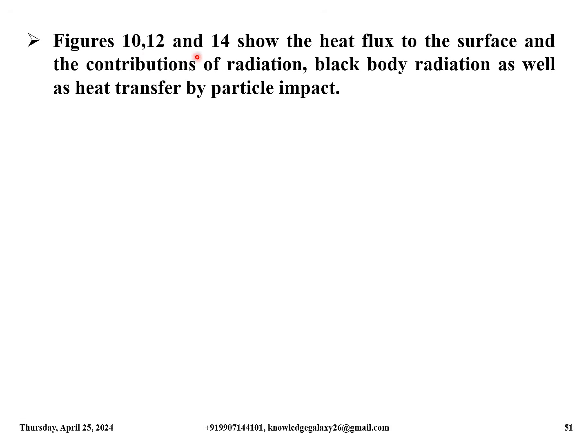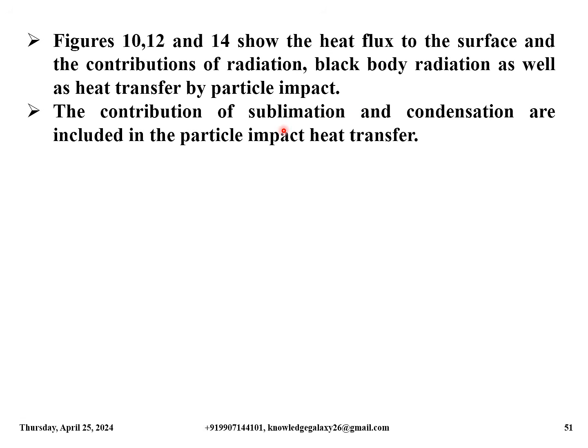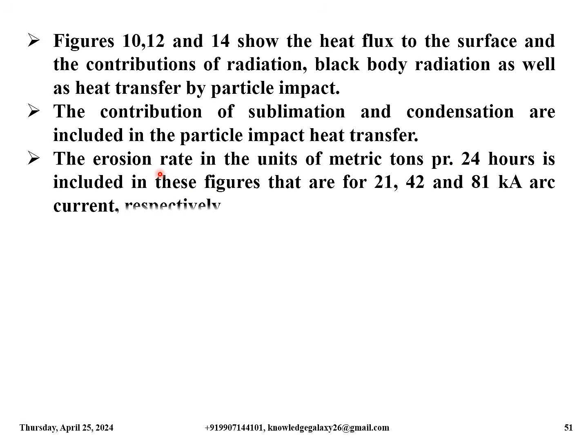Figures 10, 12 and 14 show the heat flux to the surface and the contributions of radiation, black body radiation as well as heat transfer by particle impact. The contribution of sublimation and condensation are included in the particle impact heat transfer. The erosion rate in units of metric tons per 24 hours is included in these figures that are for 21, 42 and 81 kiloampere arc currents respectively.